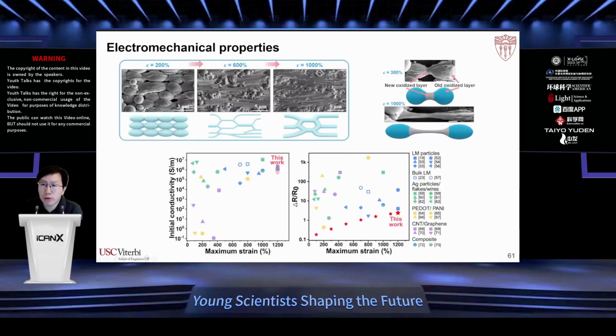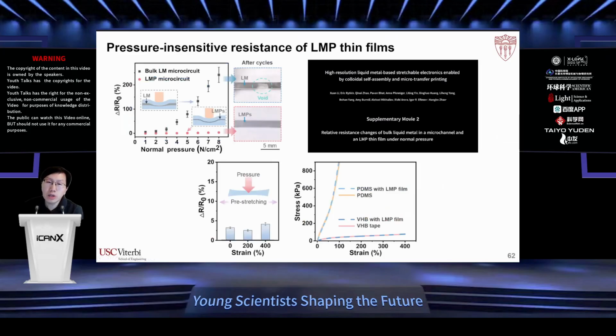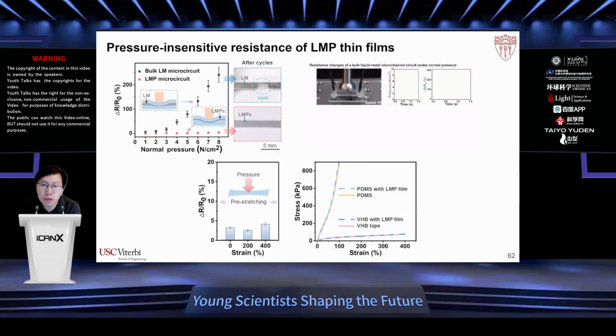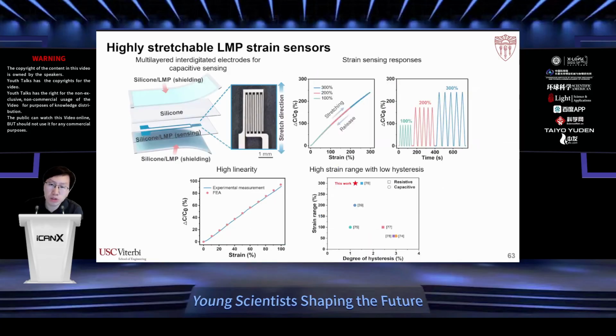And we studied how different morphology may affect the final resistance. But you can see the resistance change is really small, much smaller than many other conventional conductors. In this case, we also show that because we have a very thin layer, it's less sensitive to normal pressure. So we can use this liquid metal particle film to make strain sensors. In this case, we use an interdigital electrode design to make a capacitive strain sensor because it's less sensitive to normal pressure. So this helps us to decouple the influence of normal contact pressure.